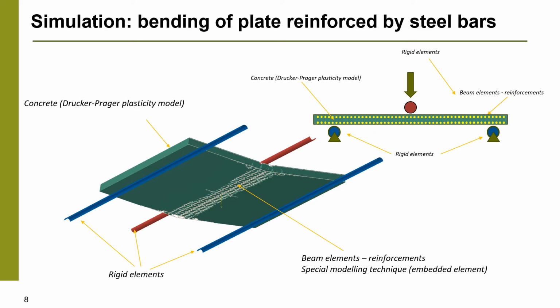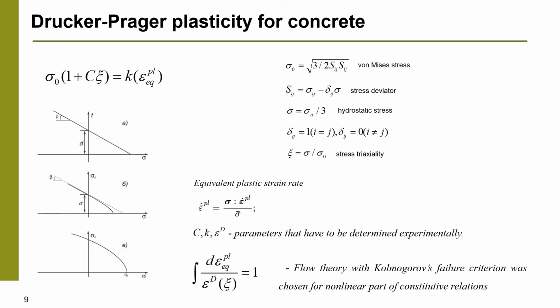We use a special modeling technique of Abaqus software, which is called embedded element, and it allows to use beam elements for bars in the solid elements for the concrete media representation. Drucker-Prager plasticity model is used for the model, and in addition a failure criterion is applied, so the structure is loaded up to failure. For the metallic components we use classic plasticity, and Drucker-Prager plasticity is used for concrete.